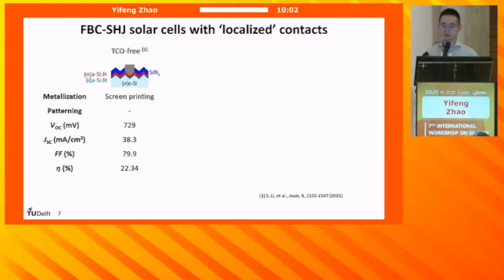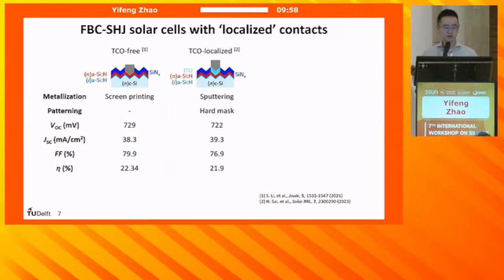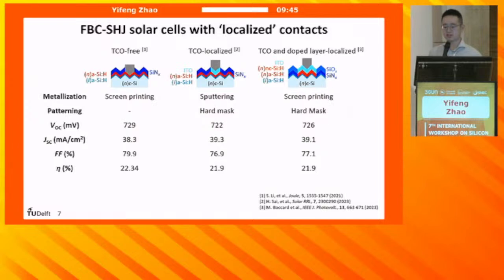So experimentally, some intermediate structures of this type of solar cells have been demonstrated. So in an attempt to fabricate TCO-free heterojunction solar cells, people have tried to remove the front TCO or localize the front TCO layer. And in both cases, the electrons are forced to laterally transport in the crystalline silicon wafer. And later on, there is a more recent study that reported the localization of both TCO and doped layers.